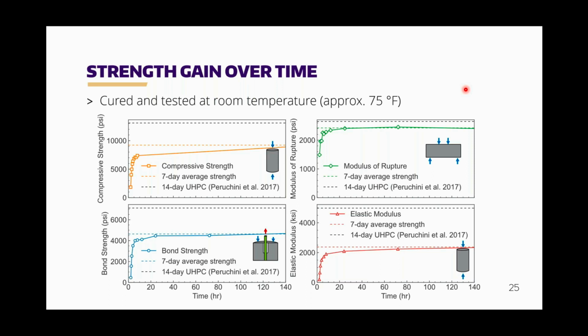These 4 plots have their strength values, so compressive strength, modulus of rupture, bond strength, and elastic modulus on the y-axis, and then here in hours time on the x-axis. We tested these pretty frequently at the early stages of curing to see that rapid rise in strength, and then like we had seen before, it levels off as we approach 7 days. Something to note from these plots is the comparison to UHPC. This is a non-proprietary UHPC strength. That's that black dashed line that you see usually at the top of the plot, showing how each of these markers of polymer concrete compares to that of UHPC.